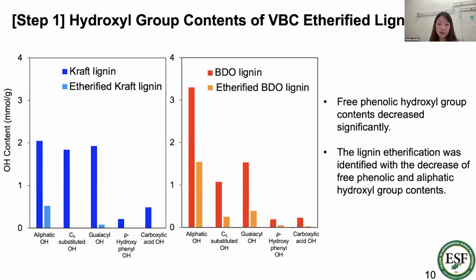And we modified, etherified the lignin for both kraft lignin and BDO lignin. There are two types of hydroxyl group contents: the aliphatic hydroxyl group contents and the phenolic hydroxyl group contents. Interestingly, for both types of lignin, the phenolic hydroxyl group contents significantly decreased, over 95%, after the modification. However, the aliphatic hydroxyl group decreased, but not as significantly as the phenolic hydroxyl group contents. So we want to see why it is different.